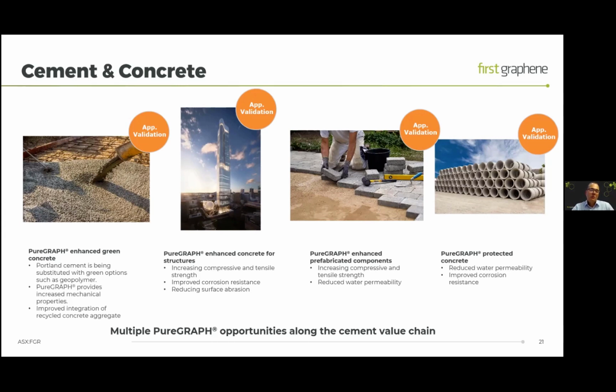The addition of graphene will also reduce water penetration and therefore improve corrosion resistance. It's also been shown to reduce surface abrasion of these concretes. Also in prefabricated components, whether from blocks to larger items, increasing the compressive and tensile strength offers opportunities to change the way these precast items are put together. And again, you also get a reduced water permeability in these systems, which is attractive.